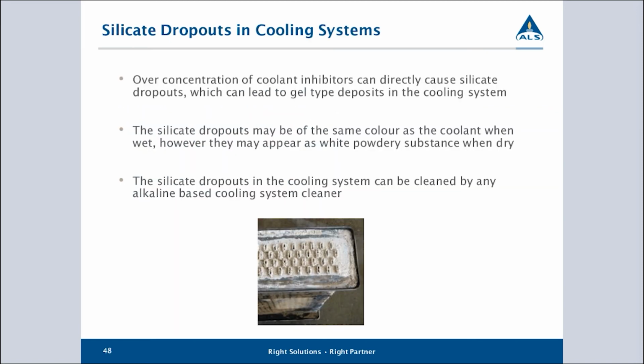We also, and this is a more common problem, have what we're looking at here, which is salts that have plated out. These salts could be coming from dirty water, or they could be coming from a mixture of coolants that have been put together, where a particular silicate can react and plate out and form these kinds of deposits in the cooling system. The main way to try and stop this from happening is to make sure that you've got the right formulation of your coolant and that you don't put tap water in, or you only use demineralized water in the cooling system if you top the system up.